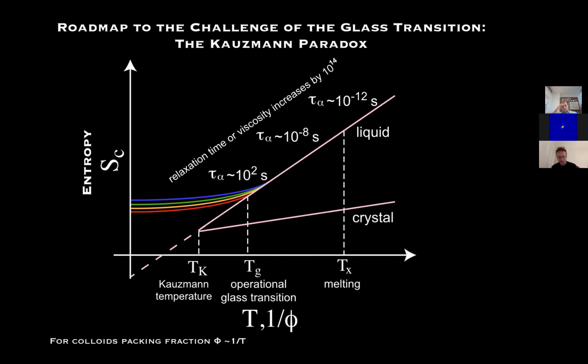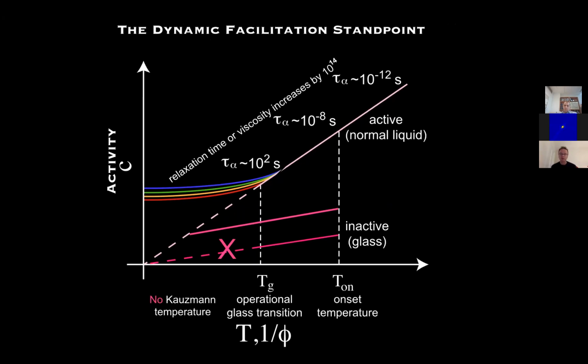And so if I now flip back to the Kauzmann picture, this actually looks kind of similar. I have got two lines. The quantity drops as I drop the temperature, and there's some lower point where they come together. So in the Kauzmann picture, or the thermodynamic picture of the glass transition, that is the Kauzmann temperature, and the entropy of the liquid and the crystal become the same thing at the Kauzmann temperature. However, in my slightly revised dynamic facilitation picture, the activity of these two phases becomes the same at some lower temperature. And it turns out that lower temperature is close to the Kauzmann temperature.